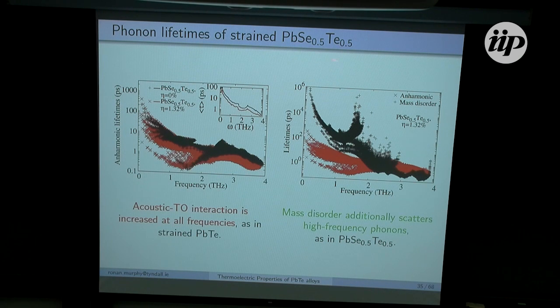Now, if we take a look, these are lifetimes due to mass disorder in black, and then due to anharmonic processes in red. And we see that the introduction of mass disorder in the alloy really helps to scatter those high-frequency phonons above 2 terahertz, whereas the lower frequency lifetimes below 2 terahertz are really scattered by the anharmonic processes. So by increasing the proximity of this alloy to the phase transition, you can really help to target the scattering of those low-frequency phonons.